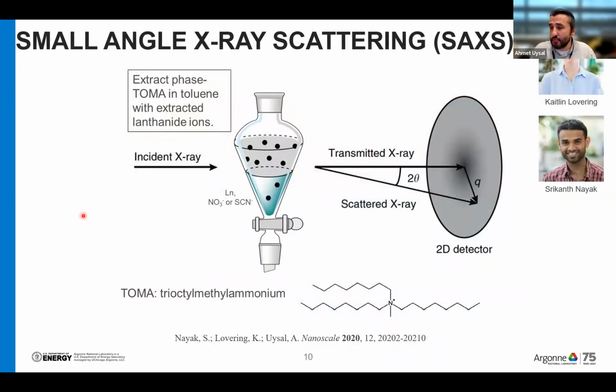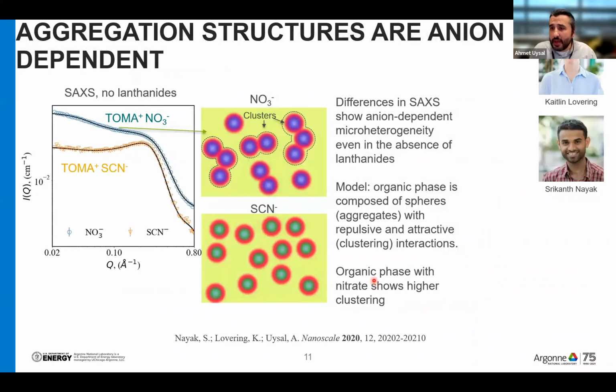One thing we can do is do the extraction as prescribed. This is a known process, by the way, in the literature. Everybody knows this, but nobody understands why it is happening in that way. So we can do this extraction, and we can look at the organic phase with small angle X-ray scattering. And we start without any metal ions because we are trying to understand the differences between nitrate and thiocyanate. So let's just contact our organic phase with a nitrate or thiocyanate solution and look at what kind of structures form in the organic phase. And it is already very interesting.